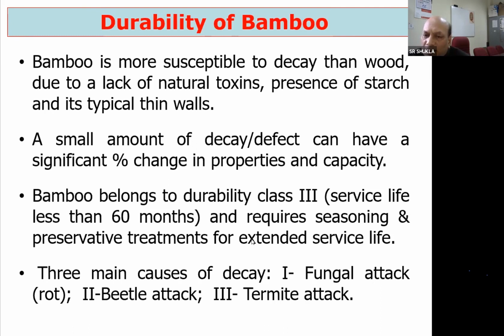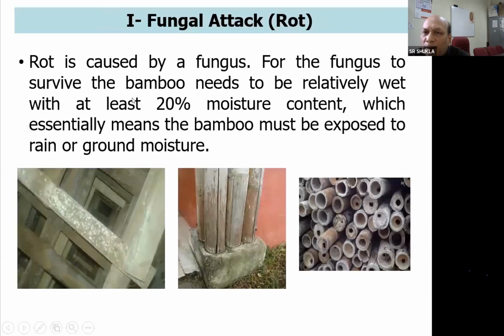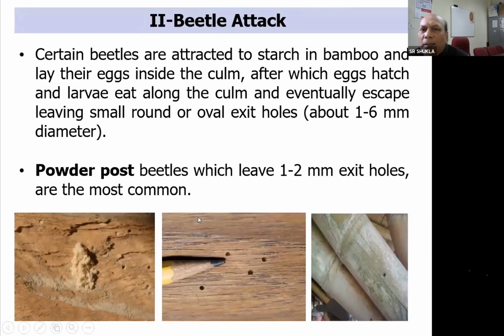One is the fungal attack, another is the beetle or borer attack, and third is the termite attack. This is the fungal attack, where fungus starts rotting the bamboo when moisture is around 20% and moderate temperature is there. So this moisture needs to be removed from the bamboo so that it does not get affected by the fungal attack. And second is the borer attack.